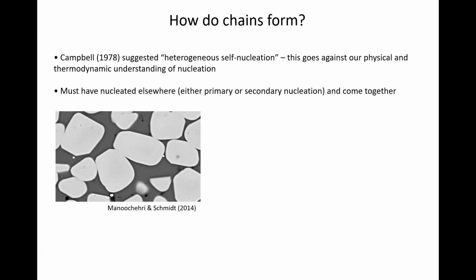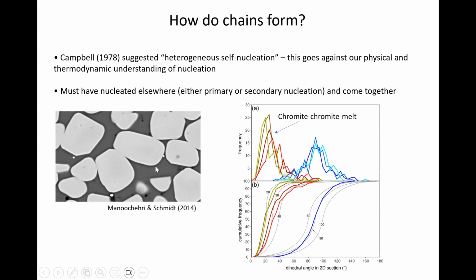Well, this is where we need to look at experiments and think about what's the physics going on in a system where we've got more than 2 grains of chromite. Now, these are some beautiful experiments which were done by one of Max Schmidt's students in his trilogy of compaction experiments. They're very, very lovely. So these are chromite crystals, and they're nice and rounded because they're texture equilibrated, so we can measure the dihedral angle between the chromites and the glass.